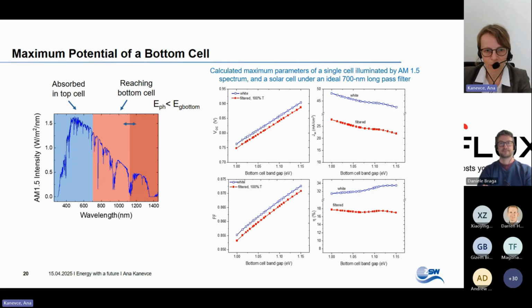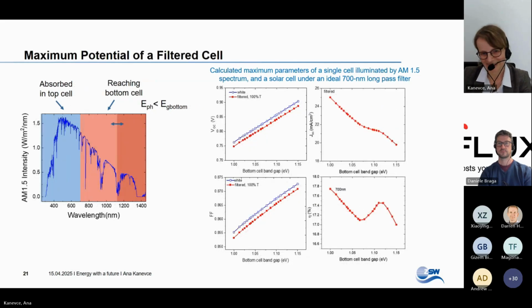We lose current, of course, compared to a single cell. We lose voltage because of decreased quasi-Fermi level splitting. The efficiency doesn't look very dependent on the band gap variation. Let me zoom this in. Because of the absorption bands in the AM 1.5 spectrum, we do not have a monotonic dependence of the band gap on the bottom cell performance.